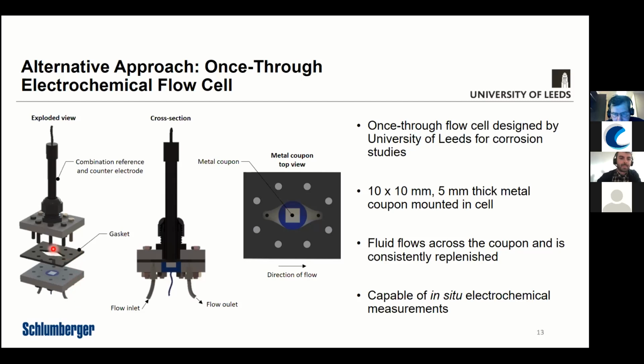And then in between that, we have a gasket. The gasket is mainly used to seal the flow cell and to channel the fluid flow across the coupon. So once we seal that together, we essentially create a very controllable environment, as I said, where the fluid will flow into the cell. The corrosion reactions and the inhibition process are all happening within this particular environment.